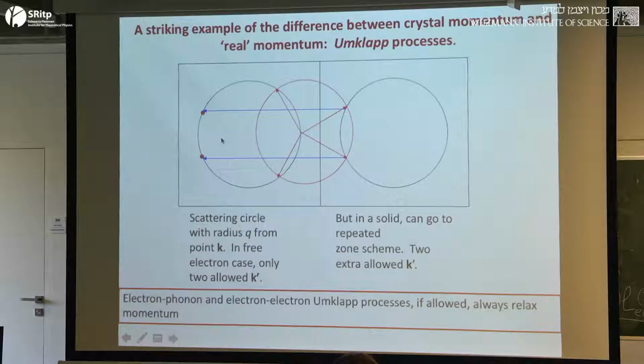Any umklapp process, if it's allowed to happen, should be thought of as momentum relaxing in a solid. So all umklapp processes are definitely the enemy of electron hydrodynamics in a real material. Now what you'll also see is that there's a geometric criterion for this to happen. If the scatterer had only a very low Q here, then you would have a scattering circle which would no longer intersect the next Brillouin zone, so you'd be able to cut out these umklapp processes. Right? But certainly when you're going up towards real metals with large Fermi surfaces, you've got to be very careful about thinking about the consequences of umklapp when you're thinking about your idealized attempts to see electronic hydrodynamics.